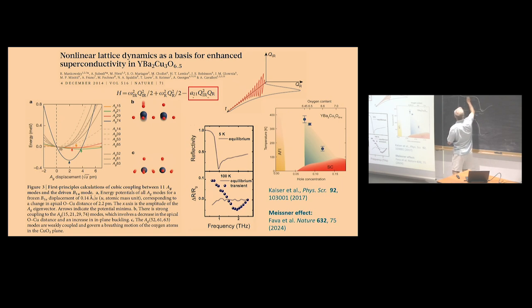And then, in classical BCS superconductors, there will be a decrease of conductivity at the band gap. Decrease of conductivity, and then, because the integral of conductivity should be constant, temperature independent, what you lose here is transferred to a zero frequency delta function. So the integral of conductivity is constant, but there is a delta function, so you have infinite conductivity at zero frequency.